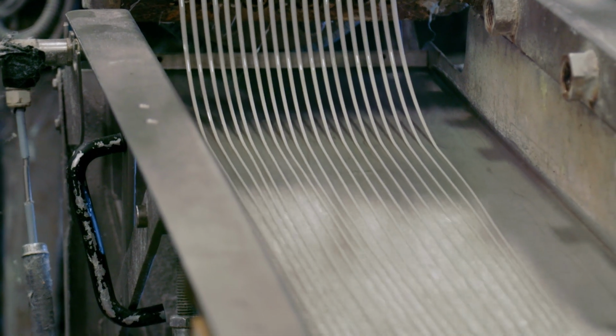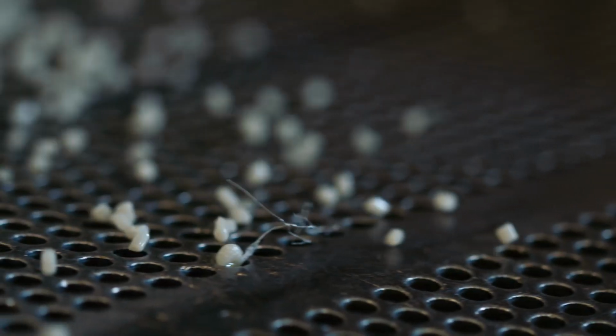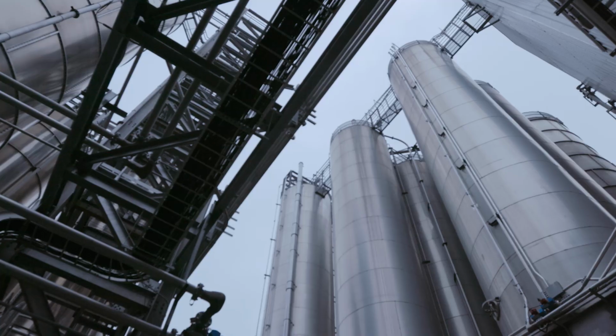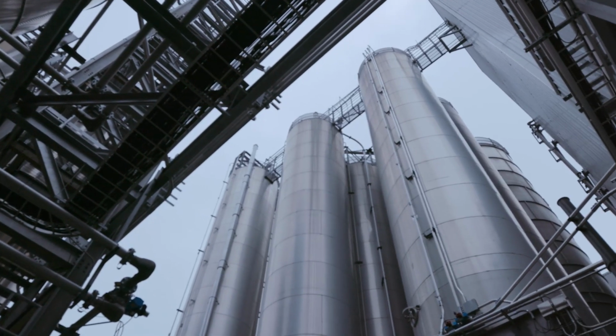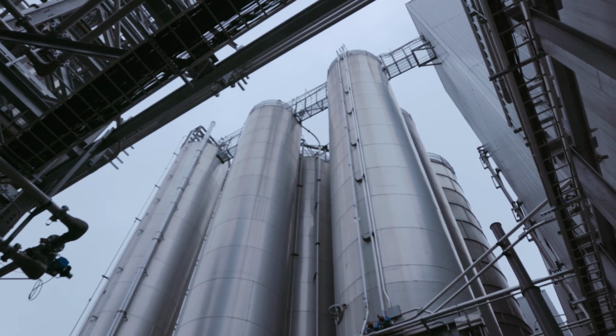The 10mm thick molten filaments discharge into a water trough, which cools and hardens the plastic. The strands flow under the knife of a chopper, which cuts them into 5mm sized chips. The chips air dry and tumble through a grate. Powerful fans channel the chips into storage silos. Each silo holds about 27 million recycled plastic bottles.